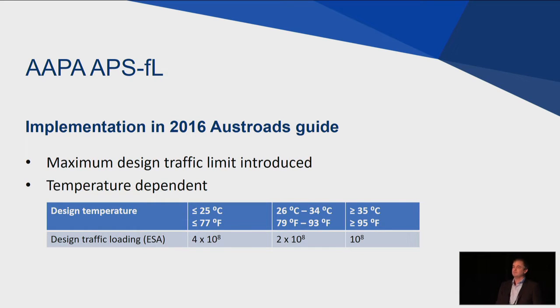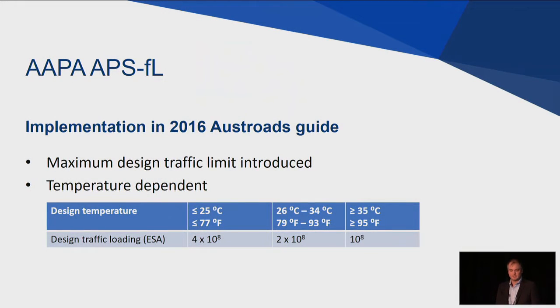Now in terms of incorporation into our national design method, that did run into a couple of problems. Like I said, the procedures they followed were very heavily geared towards the use of the dynamic compressive modulus, which is not really compatible with the Austroads design method. And as a result, all that could be done was run a lot of comparative analysis. And in the end, the road agencies were only comfortable with introducing a maximum design traffic limit in the design guide based on some of this comparative analysis. So basically the agreement is that you do not design your pavements for more than these maximum design traffic limits, and therefore you're basically limiting the thickness of your asphalt pavement.